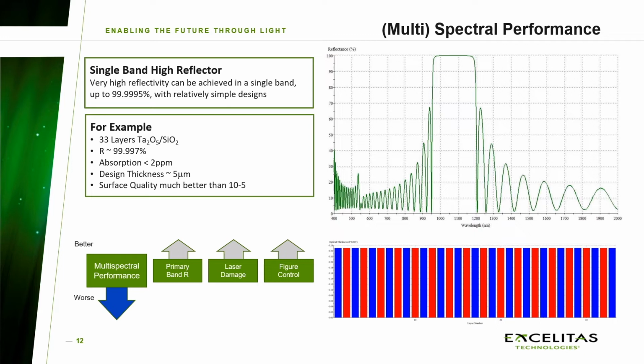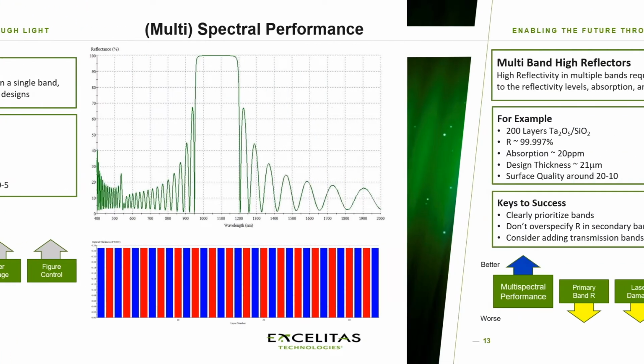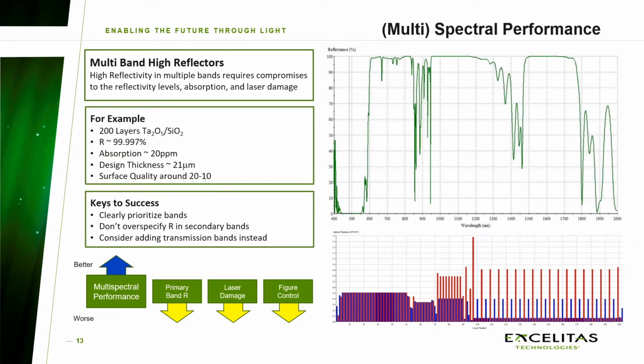If we want to be able to manage multiple bands, obviously we've got to get a little bit more sophisticated in our design. And that's where things can get pretty tricky. Here's an example of a multi-band reflector that has bands in the visible. It has a pretty wide band in the near infrared in order to accommodate a spectrally beam combined high energy laser source. And then it's got another reflection band up around 1700 nanometers for some other laser functionality. Putting all three bands together, having the width of these bands be fairly critical, creates a pretty challenging design problem.